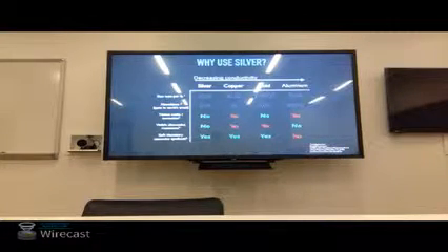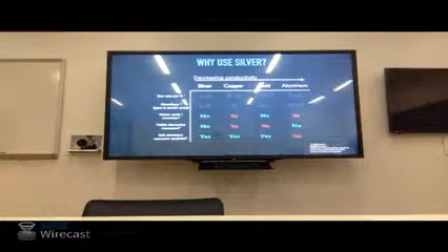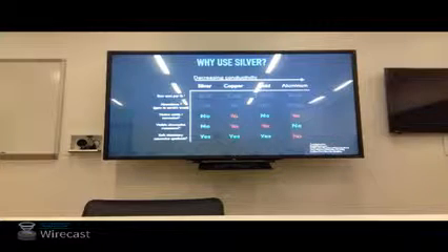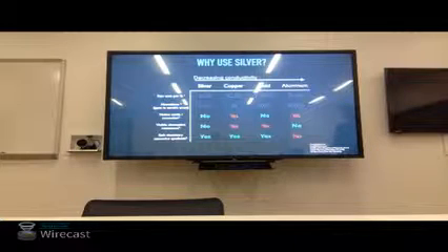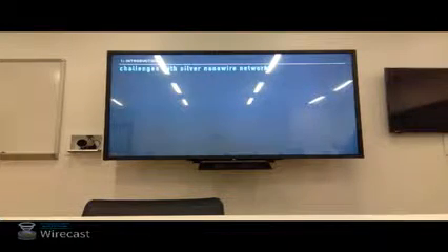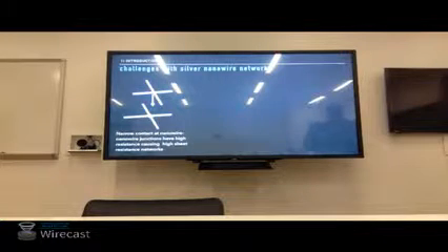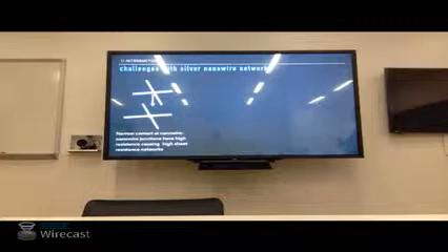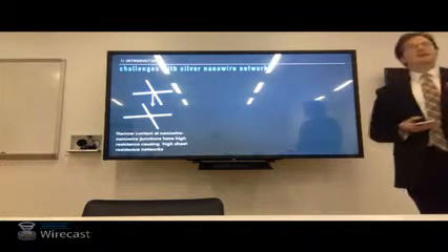And perhaps most importantly, we need a good way to make these things in a vat process where we can scale it easily. So when we add in a couple more considerations, we see why silver is not only the system we employ, but widely employed throughout the literature. However, there are some challenges. So the first challenge, one that we'll come back to many times, is that narrow contact in your percolating layer between nanowires, nanowire-nanowire contact, is a source of resistance. It can lead to a very resistive, macroscopically, network.